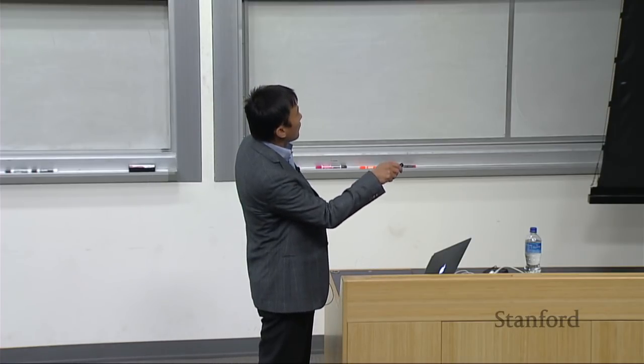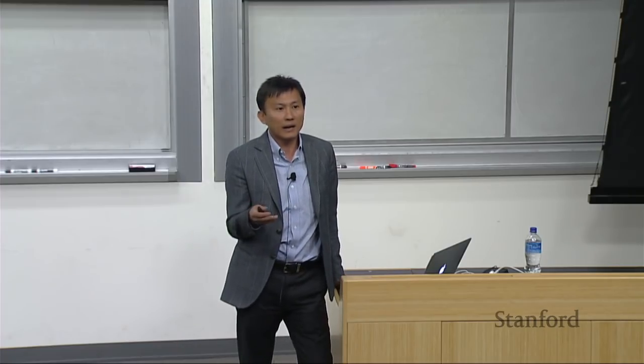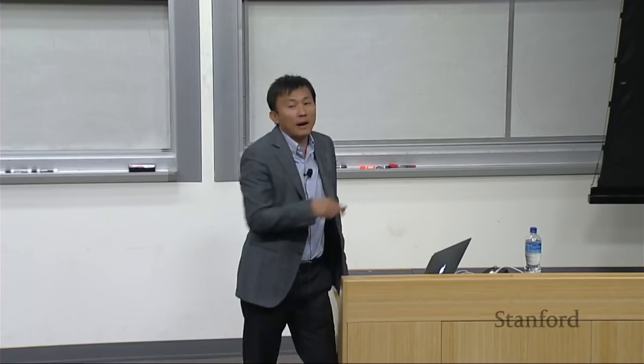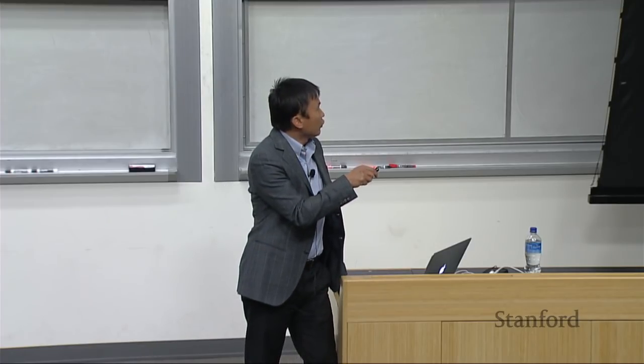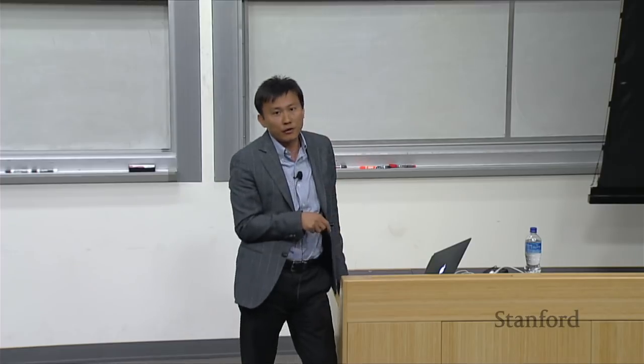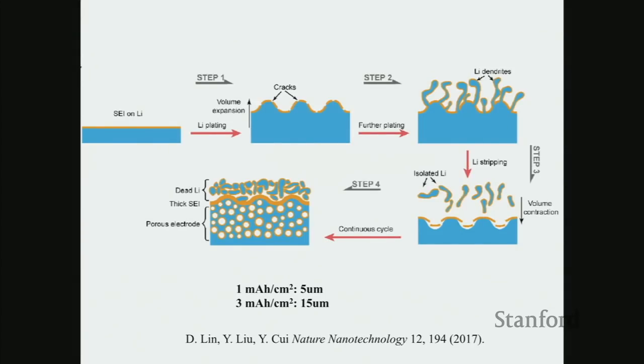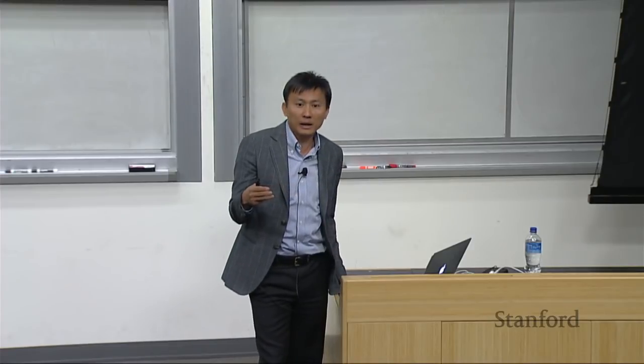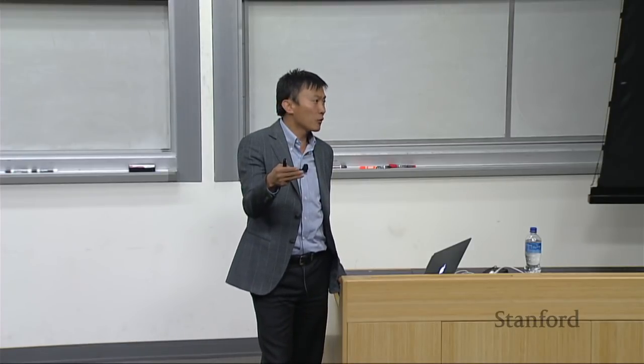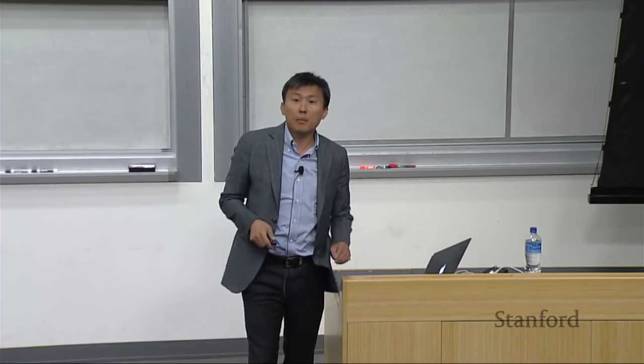That's because if you start from a lithium metal anode, it's so reactive with organic electrolyte. It forms an interfacial compound, SEI, right away. And then once you charge your battery, you need to plate lithium onto this lithium foil. There's no guarantee this interface will be flat during plating. You are going to change the surface topology. This will stretch your SEI layer and make a crack or multiple cracks on the surface. This nucleation hotspot, you will grow a filament out of this hotspot. This filament grows longer and longer, can make a battery short, punch through the separator and make the battery catch fire and explode. That was indeed a major challenge.